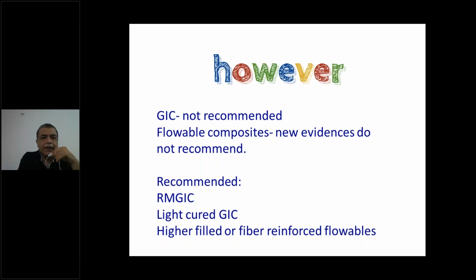However, many of the practitioners use it not as a base, but to reduce the amount of composite so that polymerization shrinkage is less, which is also called the sandwich technique. But I know many of the practitioners still use glass ionomer cement. Please note, glass ionomer cement is not recommended. The reason is the glass ionomer sets by an acid-base reaction, which takes 24 hours to complete. And you do not wait for that. You just wait for the initial setting, and then once you etch it and rinse it, it will crumble below the composite restoration, and the restoration will fail.